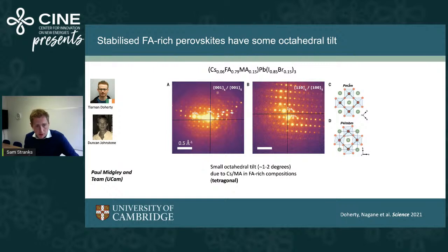And so what we see is if we look at the 001 of the cubic zone axis, when we label it in that way, we see these superstructure peaks that are labeled in white. They're quite faint, but you can see them, and they're certainly there. And so that's not consistent with the cubic space group. That's consistent with the tetragonal one. And in fact, if we look at the 110 zone axis in the cubic structure, or the cubic space group, we don't see these superstructure peaks. So these two results combined are consistent with and uniquely consistent with a tetragonal crystal structure.